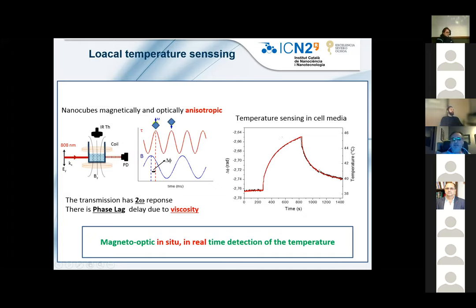This means that we can use the nanoparticles to measure magneto-optically, in situ and in real time, the temperature inside the cell media, while the infrared thermometer only measures the surface. So using this approach, we measure the inside of the cell media.